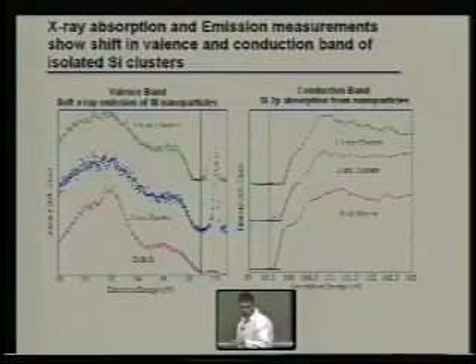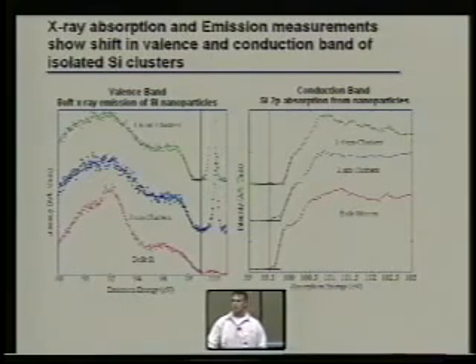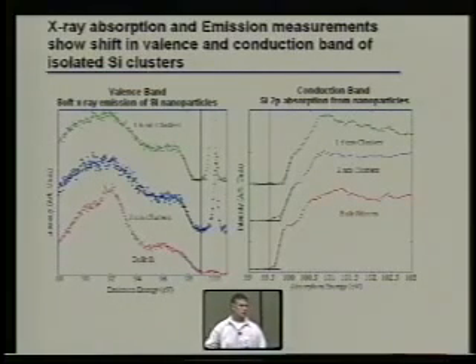So here, on the right, I show the absorption edge of bulk silicon done in total fluorescence yield mode, and 2 nanometer clusters and 1.6 nanometer clusters, and you can see that the conduction band edge is moving to higher values. And again, using soft X-ray emission, we do it also for the valence band. You see the valence band is opening up. Both of these techniques are element specific, so you know that this is actually coming from the silicon. And from the X-ray absorption techniques, you can tell the difference between silicon oxide and silicon nitride and silicon metal. So you can actually tune to the silicon, and you can prove to yourself that this is an effect of the silicon quantum dot, nothing else.